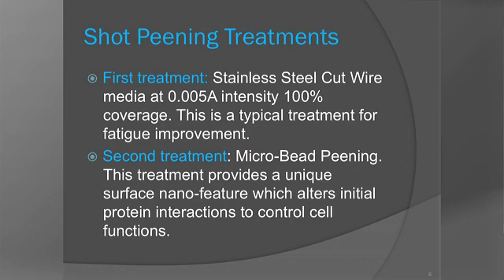A couple of routine things: shot peening is the first treatment for all of the materials, and there are five different shot peening processes I'll talk about, plus a control titanium sample that was not shot peened. In all five cases, the first step was to use a stainless steel cut wire to expose the titanium alloy. The second treatments were either a type 2 anodization process, a microbead shot peening, or a combination of both. All samples underwent this exposure to the stainless steel cut wire, and then subsequent events changed, which I'll highlight as we go through the results.